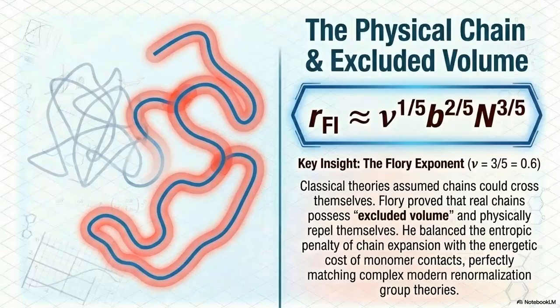The key insight here is the Flory exponent, nu equals 3/5 equals 0.6. By balancing the entropic penalty of chain expansion against the energetic cost of monomer contacts, Flory derived a simple, brilliant approximation that perfectly matches highly complex, modern renormalization group theories.